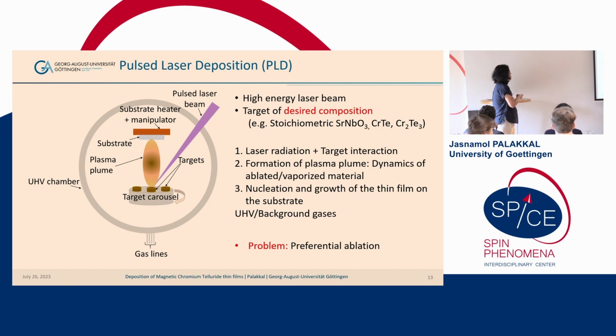In this case, the advantage is that you can use the target of the desired composition. So if you want to grow SrNbO3, you don't have to provide strontium here and niobium here and the gas surrounding, as in the case of an MBE. But in this case, you can use a stoichiometric SrNbO3 target and you can directly start the deposition.